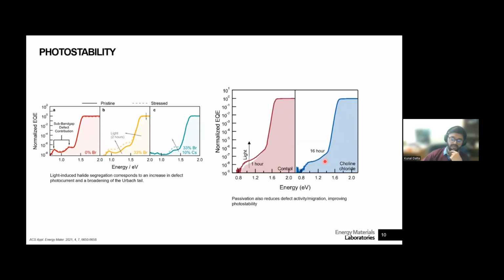And we attribute it to the choline chloride, but we don't know what kind of defects are there. There is some theory on it, but it's always a bit hard to get the defect energy correct. So we don't exactly know what kind of defects are being passivated or to what extent they are being passivated, because again, we can only observe defects that contribute to the photocurrent, right? So if there are other defects that are being passivated, we wouldn't observe them as much. But it is true, and it's quite clear, that this light-induced behavior changes significantly. So not just the voltage, but also the stability of the device changes.